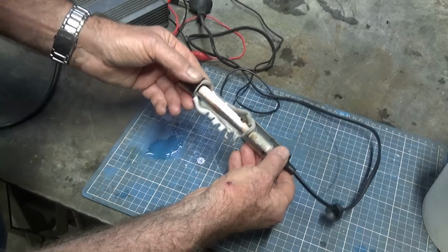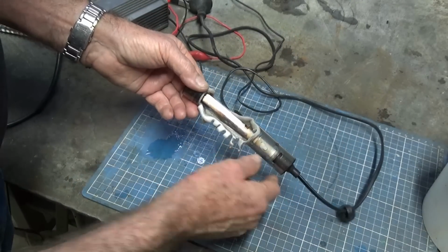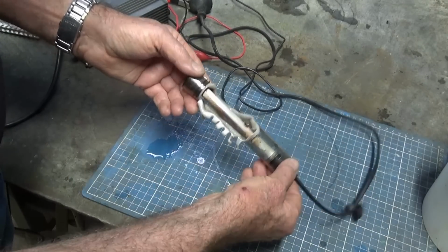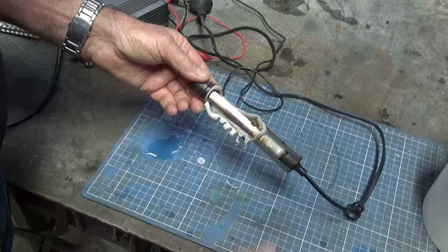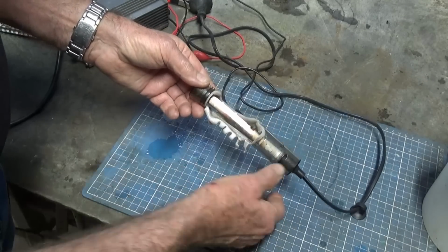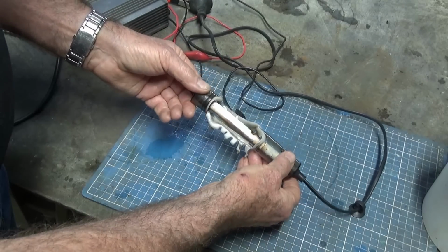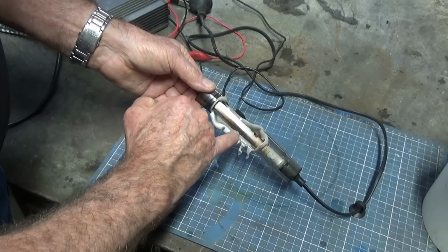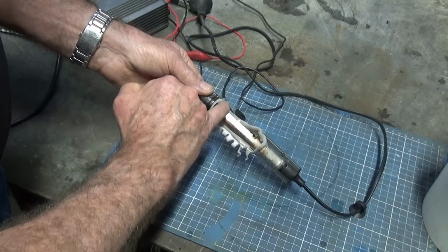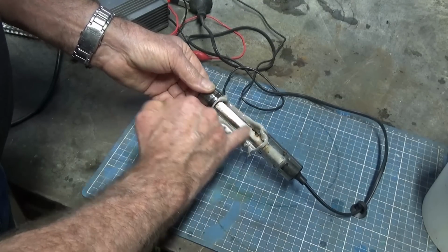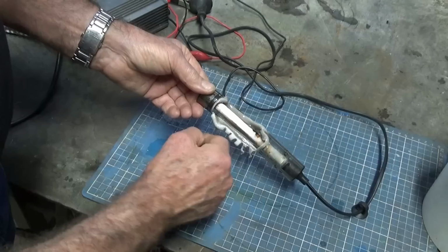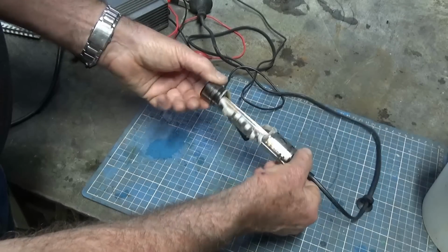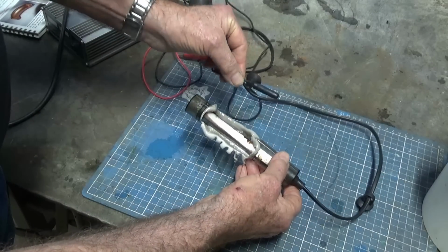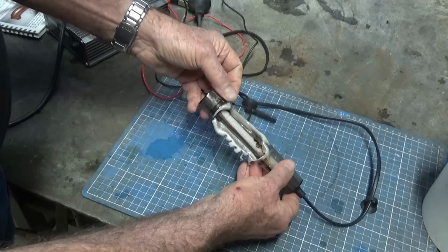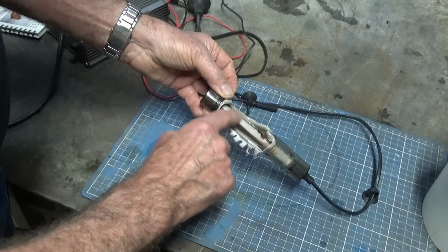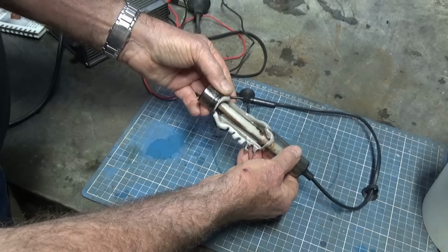Just about to pack up for the day, but I thought I'd share this with you. What happened was I took this heater out of the plating bath and I rinsed it in a bucket of water and put it down on the bench while I went and cleaned the anodes. I was only gone about 2 minutes, and I came back and heard a sizzling sound and looked to see that this quartz heating element was bright red. It's completely melted the plastic housing, and of course what happens is this sensor isn't in the liquid with the heater, so it doesn't know that this is overheating and it doesn't switch it off.